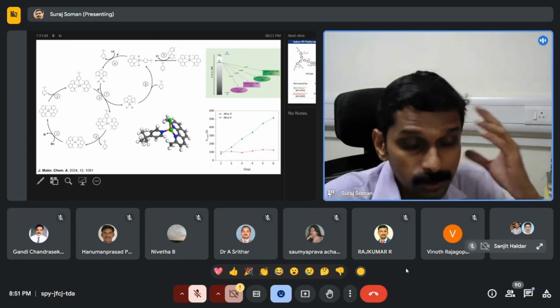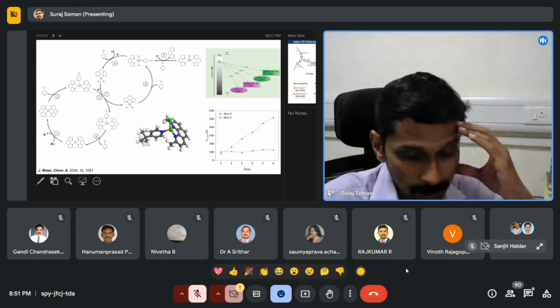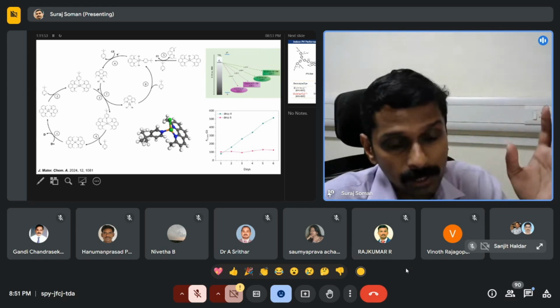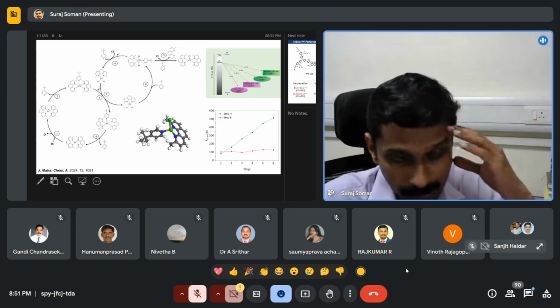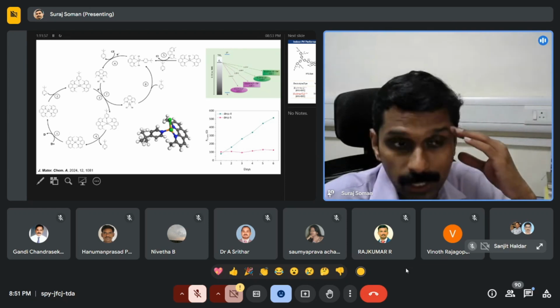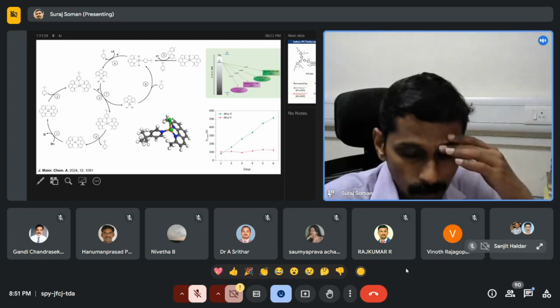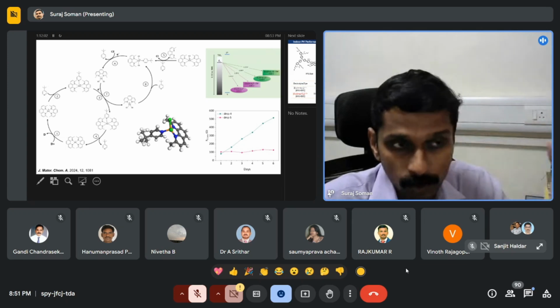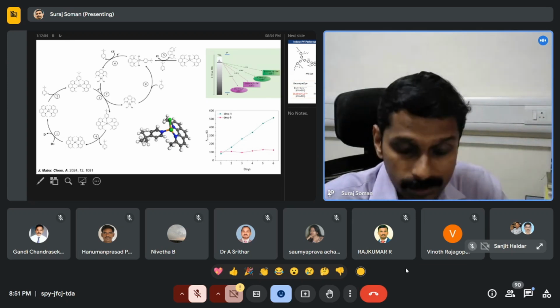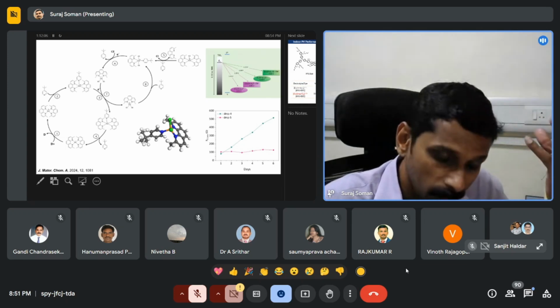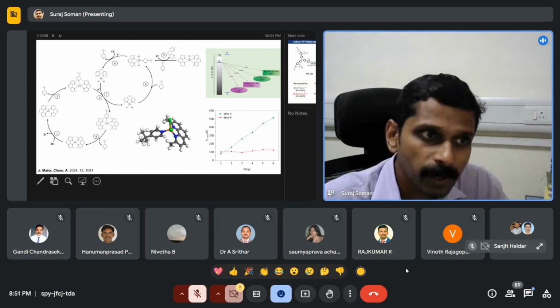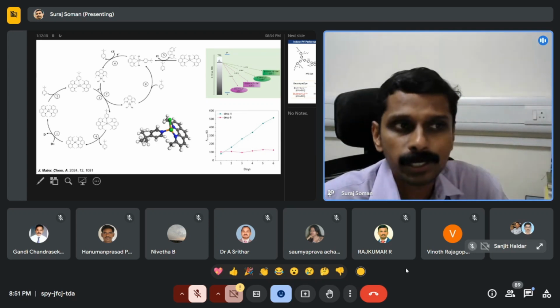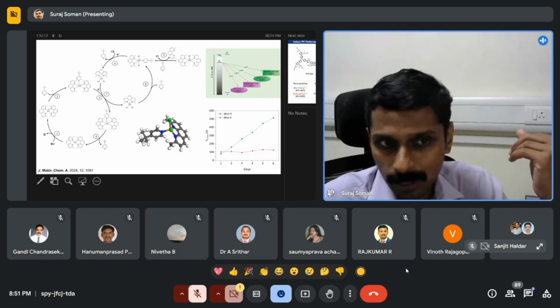It took almost 3-4 years to complete this work, where we went to find out the actual mechanism that is happening, and that was very tough, because you take the molecule, you add all the additives, then you let it crystallize, you make the single crystal, then you solve it out. And then we found a completely interesting kind of dual species mechanism coming out there.